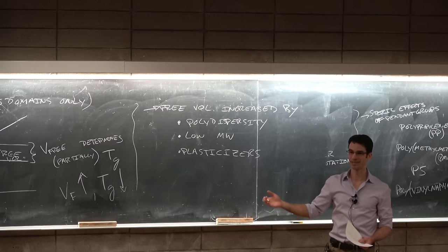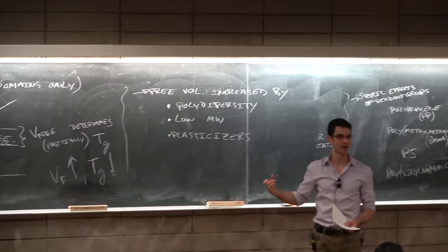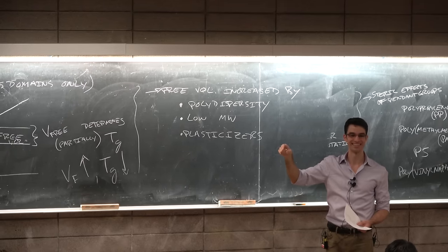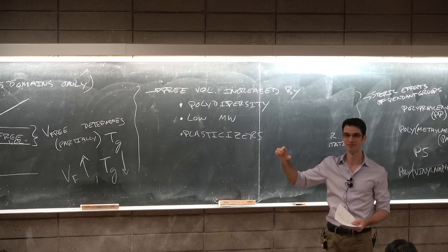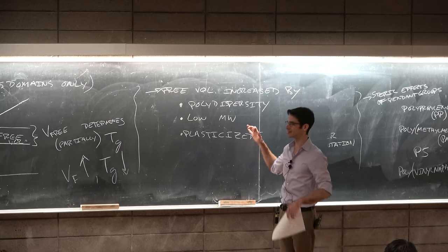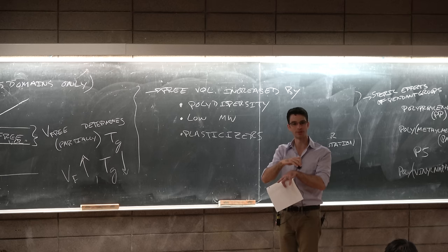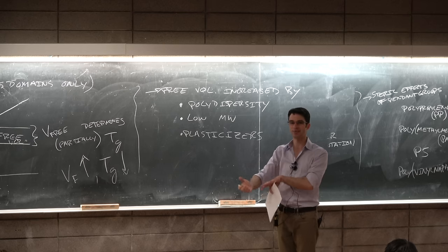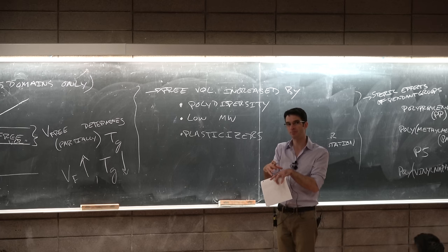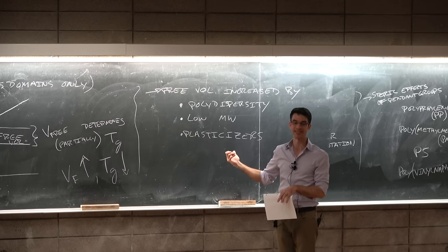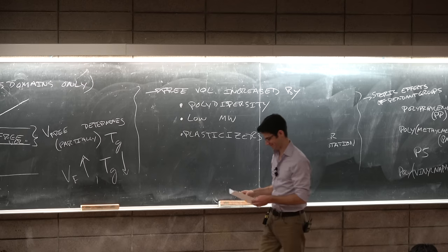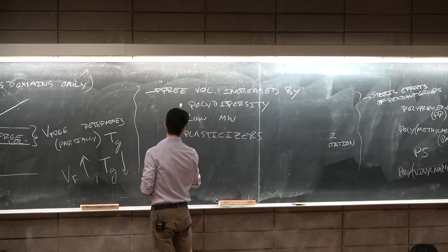But that's what it is. And over time, like if you have a really old car, if you ever notice that the soft touch plastic is now kind of brittle and has started to fracture on some of our cars, so the plasticizers are small molecules that fit their way into the polymer structure and permit the chains to slide past each other by, kind of, it's almost like providing more chain ends, higher density of chain ends, less efficient packing, more free volume. Volatile car smell, it all makes sense.